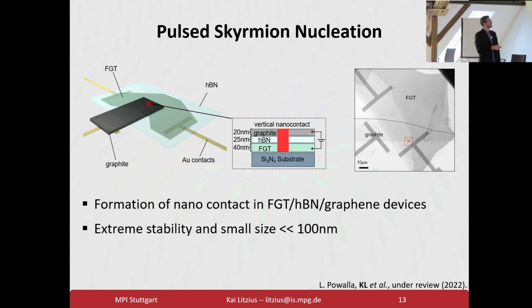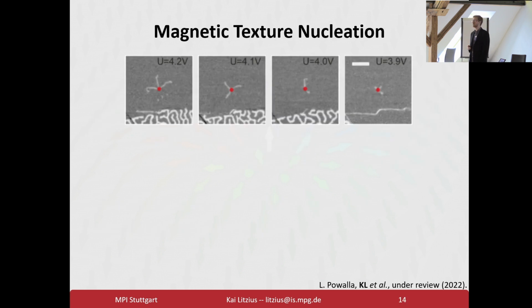This is what it looks like experimentally. So you see here the contacts. This is the big FGT flake. And here in this area, we've got a little nanocontact that then looks essentially like this. This is after passing a DC current through it, where you see a couple of stripes growing out. This is just the growth of stripes mediated by thermal effects and by current. And when you apply DC current, we always see these little stripes growing out.